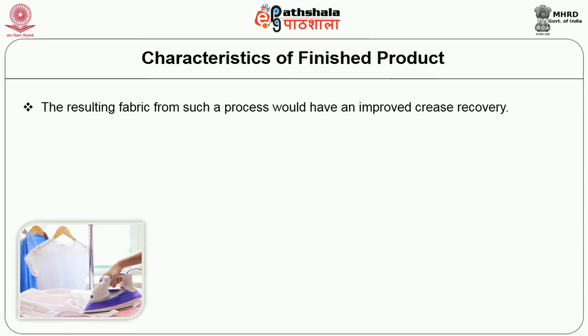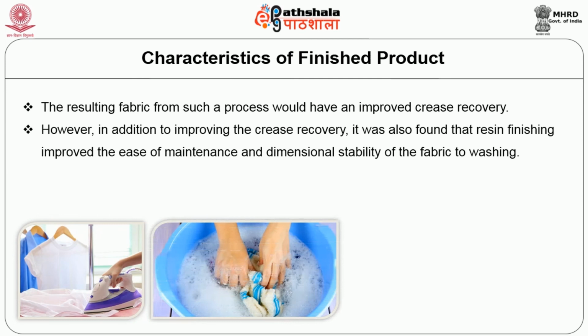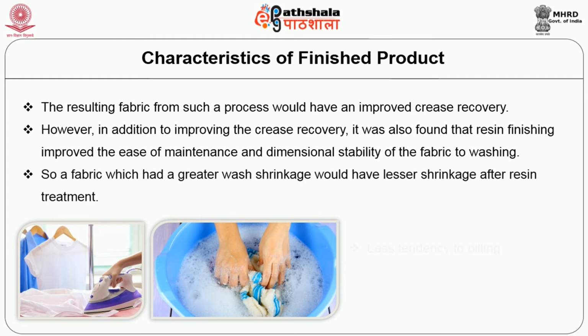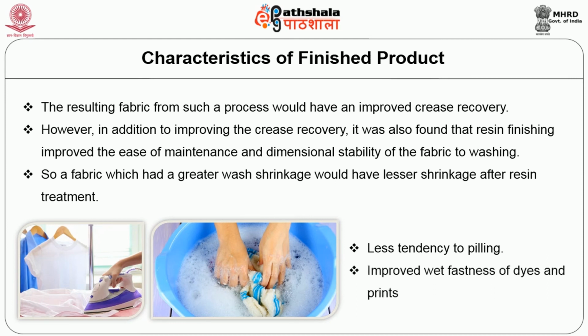Let's now have a look at the characteristics of these finished products. The resulting fabric from such a process would have an improved crease recovery. However, in addition to improving the crease recovery, it was also found that resin finishing improved the ease of maintenance and dimensional stability of the fabric to washing. So, a fabric which had a greater wash shrinkage would have lesser shrinkage after the resin treatment. It has less tendency to pilling and improved wet fastness of dyes and prints.